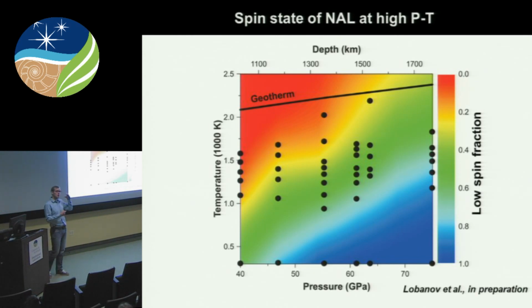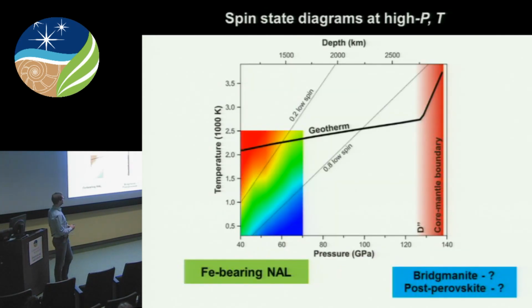And these are very unique because, as I said earlier, X-ray emission spectroscopy is not easy to combine with laser heating experiments, and therefore high temperature spin state diagrams that are constructed via experimental methods are very unique. And now we have a new tool that can allow for such diagrams. And here what you see is just the fraction of low spin in the NAL. So the blue color simply tells you low spin, red color tells you high spin.